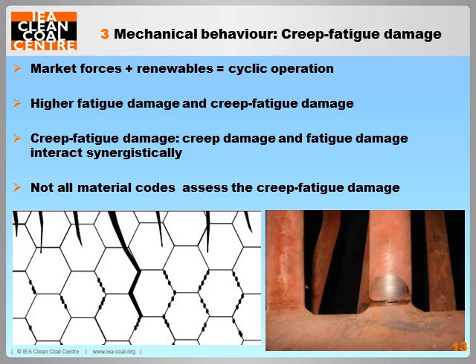Cyclic operation has resulted in higher fatigue damage of high temperature components, but also creep fatigue damage. Creep fatigue damage is where creep damage and fatigue damage interact synergistically, which can result in failure sooner than either creep or fatigue damage alone. Creep fatigue damage has been a significant cause of failures in T91. It is important to note that not all material codes currently assess creep fatigue damage.